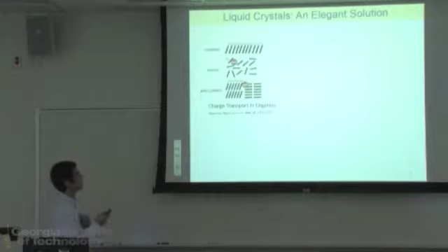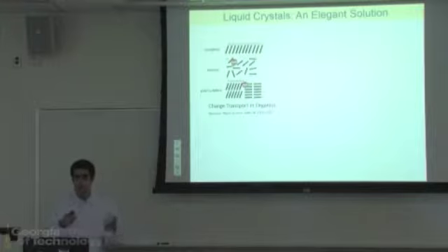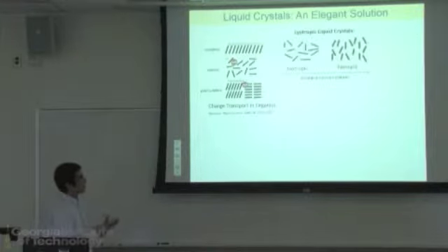On the other hand, in reality, we do have polycrystalline materials a lot of the time. So we don't get these perfectly crystalline materials. Over a large scale, you have these multiple grains, and the barriers between these grains act as barriers for the charge transport through the material. So what if we can take a liquid crystal, which is kind of intermediate ordering? In this case, you have something that's not isotropic, but not perfectly crystalline. We have something in between, this nematic phase.